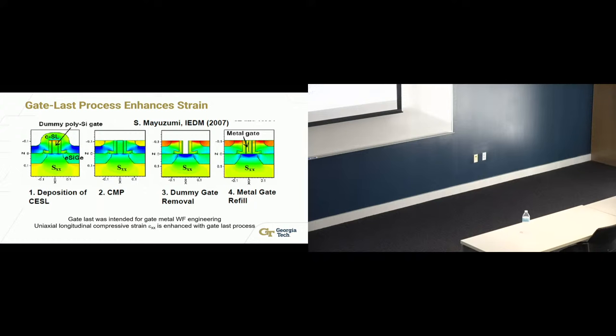So what we had to do was to come back, start with a dummy gate, finish all your high temperature source and drain activation process, come back, polish off, so that we had to work with CMP people who have never seen how to stop within 100 nanometers. They said that CMP is sandpaper, essentially, right? This was the first time we challenged them to come up with a polishing module where they can stop on a dime within 50 nanometers, otherwise you're going to polish off that entire gate, right? Or you're going to leave something unpolished. So anyway, that was the poly opening polish. Then we rip off with a selective wet etch, we take off that polysilicon, and then we fill it with the metal. Source and drain already in place, so you avoid that high temperature step.